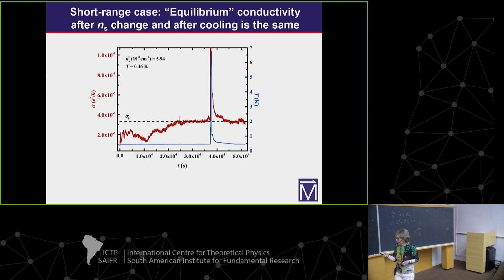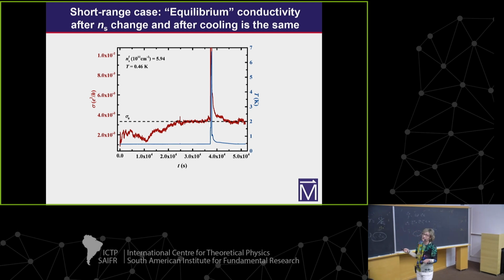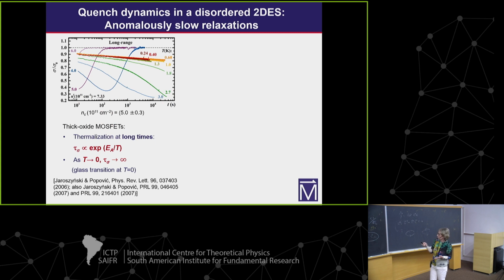Okay, so now let's compare the dynamics in these two cases. This is another example of what I discussed earlier. This is a case of a long-range interaction for a different density. I'm plotting deviation from the equilibrium value, shown by this dashed line at the top for each of the curves. So this is what we found earlier, that this approach to equilibrium depends exponentially on temperature.